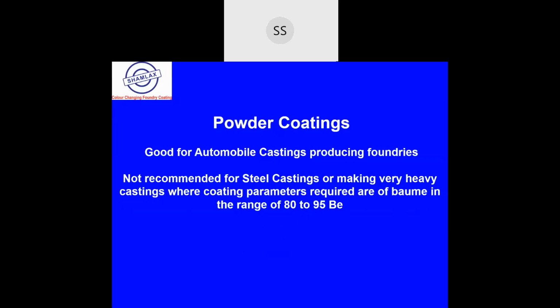Powder coatings, as I already told you, are good for automobile casting producing foundries, not recommended for steel castings or very heavy castings, where the coating parameters required are a baume in the range of 80 to 95. Because if you are producing a coating using powder coatings at around 70 baume, then you will have to apply multiple coats, and that is not advisable. It's better to have 90, 95 baume and a good coating thickness.